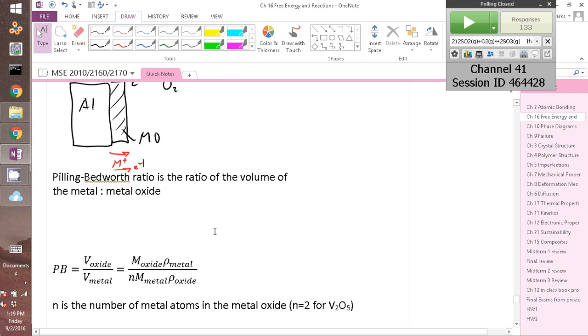There's too much strain. Strain has an energy component with it, and so it's going to spall off. Have you ever heard that word spall? It's when you form an oxide, but it's not adhering very well below it simply because of size. You can't accommodate the same number. And if I'm too small, the same problem happens. If somebody's really skinny, you're trying to match them up with the same number of rows, you're going to get strain. So if it's too small or too big, you get a layer that's going to fall off easily. As soon as this oxide layer chips off, you've got exposed metal again, you can turn those into oxides and the process repeats itself.